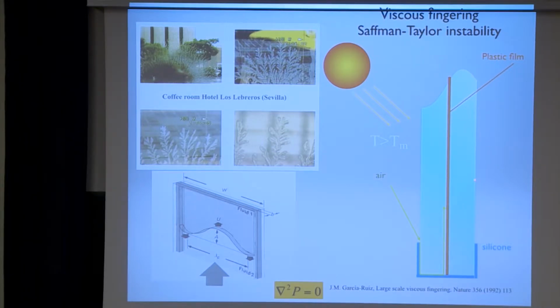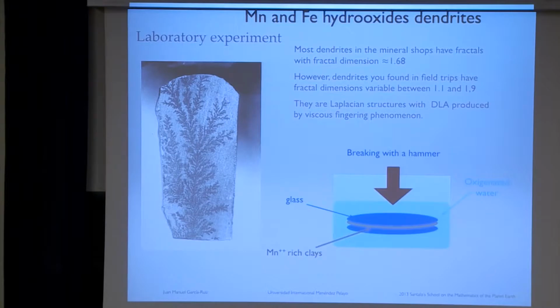So the plastic film melts, and then what happens is that you have air, which is a low viscosity fluid, pushing a fluid of higher viscosity, which is the plastic. And when this happens, this is what is called the Saffman-Taylor instability. So what happens is that you create this kind of morphology, this branching, that looks exactly, and has the same fractal dimension, as the pyrolusite dendrite. So maybe, okay, you say, how could this be applied to the formation of the mineral dendrite?